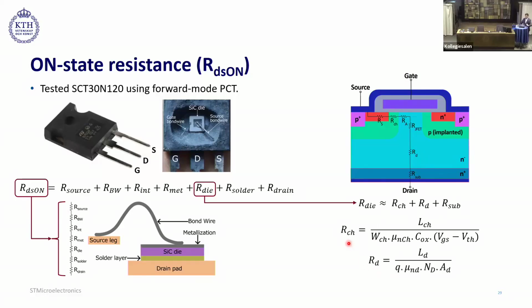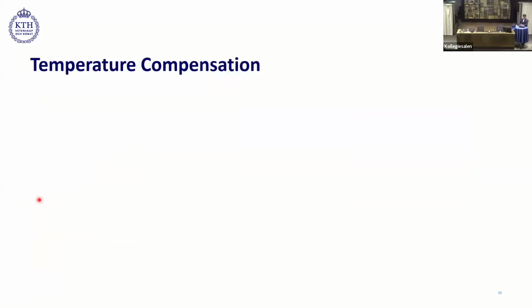If you look at the channel resistance, then we see that it also depends on gate to source voltage and threshold voltage. It's important to note that the threshold voltage drifts during power cycling because of bias temperature instability, which also eventually results in R channel and RDS on drift, which we will observe later as well. So first, we started with the temperature compensation method in order to remove any temperature-related effects from this parameter.